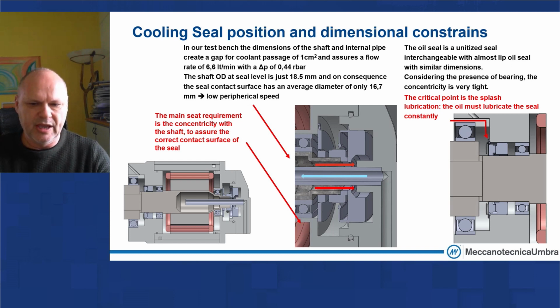With this solution, we are able to avoid or reduce much the leakage due to the centrifugal effect, because in this case the fluid is inside the mechanical seal. So during the rotation at a very, very high speed, the centrifugal force on the fluid between the sliding phase of mechanical seal increases the leakage rate. So to reduce this effect, it is important to have a design of the shaft in the seal chamber as small as possible.